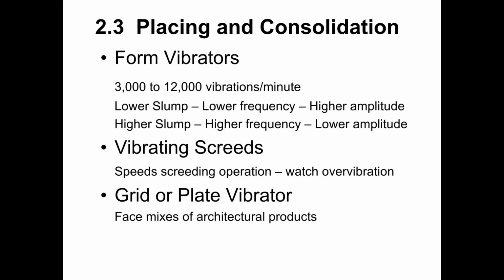Another method of consolidation is a grid or plate vibrator. You most commonly see these used in architectural production to consolidate the face mix of an architectural panel. What these look like is you either have a steel plate or a grid that maybe is between 1 and 2 square feet of coverage. It has a vibrator attached to it and a handle so that a worker actually gets into the form after the face mix has been cast and smoothed. They walk on that concrete and they place this grid or plate vibrator down and allow it to vibrate every square foot of that face mix for a set number of seconds.